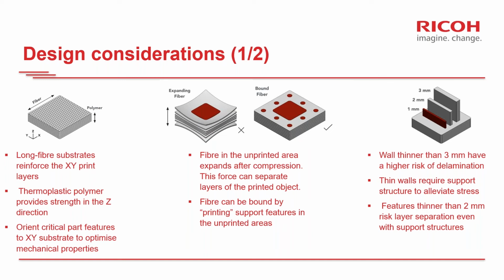Also, as Mark mentioned, when describing the different steps of the process, during the consolidation step, the parts are heated under load. And once the load is removed, the fibers tend to expand a bit like a spring. So this could lead to layer separation in the parts. In order to avoid that layer separation, the fibers can be bound by printing what we call support features, which are not exactly the same as the support features that people are familiar with when looking at some metal process or SLA process. Those support features actually are printed in unprinted areas, like in the image you can see here, the second image in the middle, and their function is just to keep the fibers together when you remove the load.